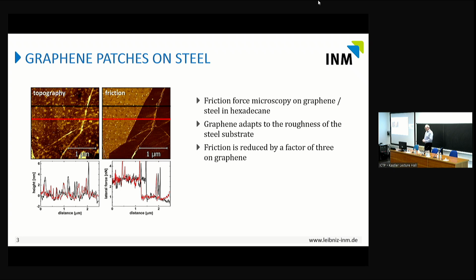So what you can see here is images. On the left is a topography image, on the right is a friction image. The steel has a certain remaining roughness, for sure. And what you can see is that there is actually graphene on the right side of the frame and no graphene on the left. And we see that only in friction. In topography, it's impossible to see this one layer graphene. But in friction, you see that the friction is actually greatly reduced. These are measurements in hexadecane with a sharp AFM tip. So we have a reduction of a factor of 3 on the graphene.